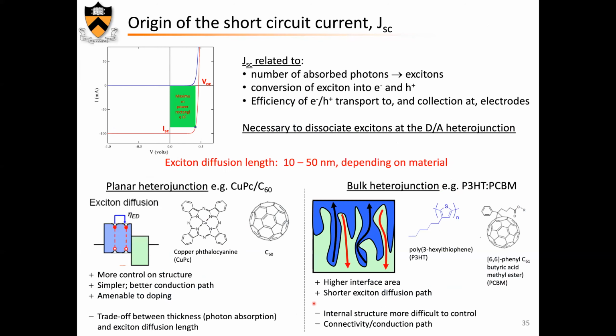So this being considered, one big step that occurred many years ago was to go from the single interface device, where you have the donor on top of which you put the acceptor, to a bulk heterojunction. Why do you do that? I mean, if you look at this structure here, of course, you have more control on the structure and maybe on the mobility of the material. It's somewhat simpler, and eventually you can dope the materials.